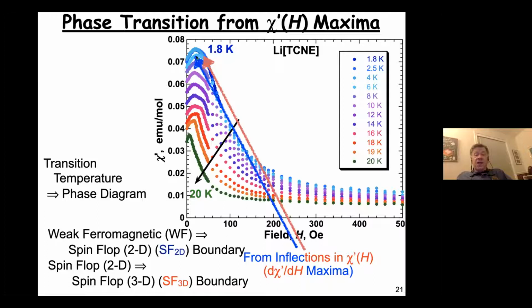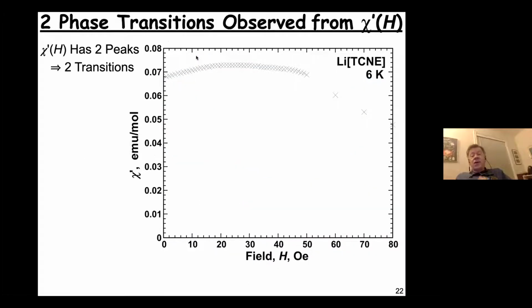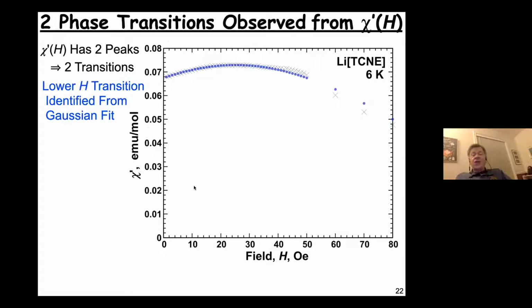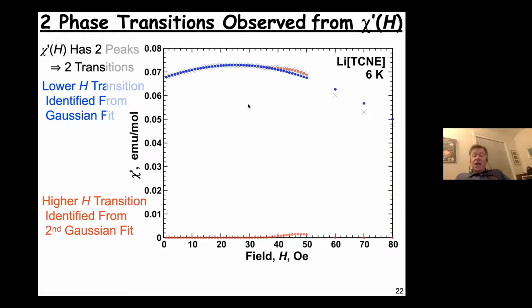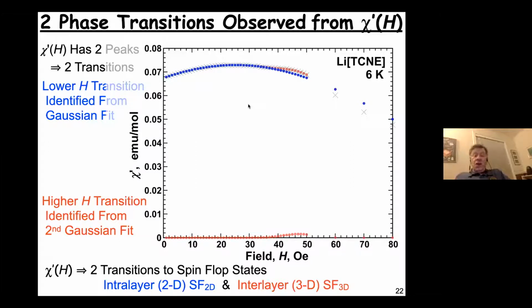And you can see that's basically taken from the maximum. We've actually done it from the derivative. It's more convenient. And I'll just show you how we accumulated some of the data. And here is the data at 6 Kelvin in X's, and you can see the chi prime of H is simply shown here. And now we're going to fit it to a Gaussian to show the maximum for the lower field data. But you can see there's a divergence at slightly higher field, and we have to invoke a second Gaussian curve so that we have 2 Gaussian curves, 2 maxima, indicative of 2 transitions for this material. So we see the lower field one going from a weak ferromagnet to a 2D spin flop, and then a little higher field going from the 2D spin flop transition to the 3D spin flop transition.